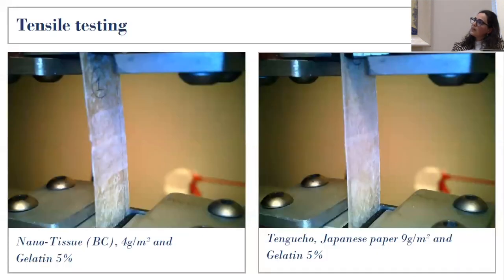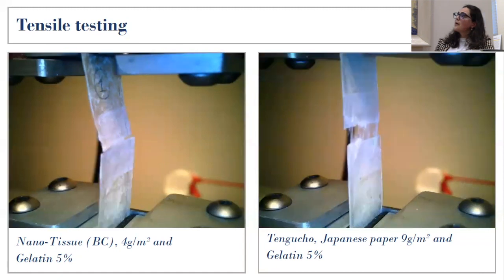But what we have found very useful is also to look with a micro camera at how the mending material breaks under the tension of the instrument. Next slide, please. So, for example, in this slide you can compare. In both cases, the material was pre-coated with gelatin at 5%. But in one case, we are seeing the mending, the repair that was made with bacterial cellulose, and in the second case, the repair was made with tengucho, Japanese paper. So we can see the difference.